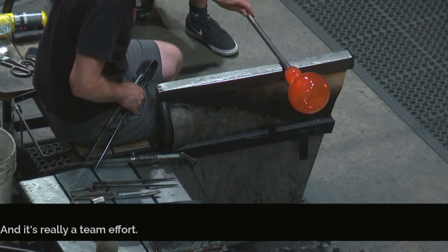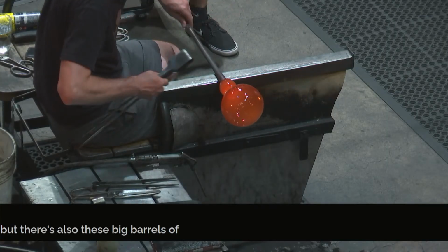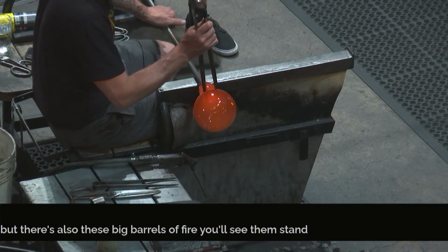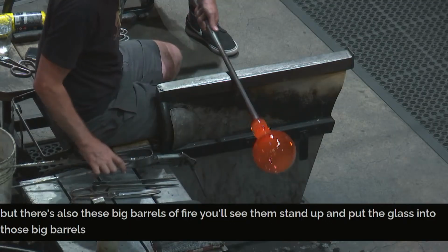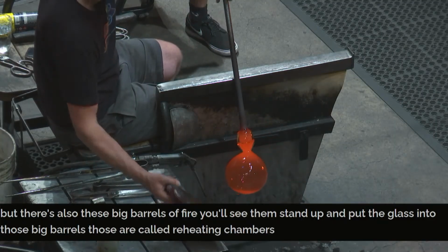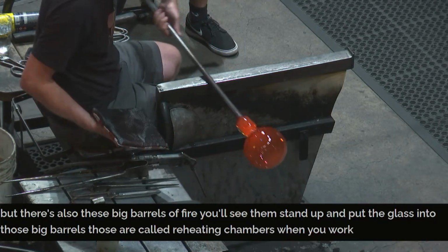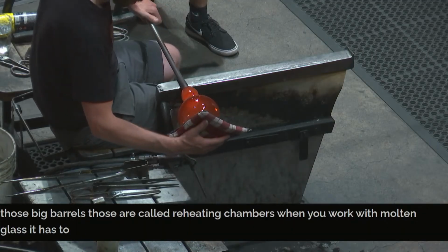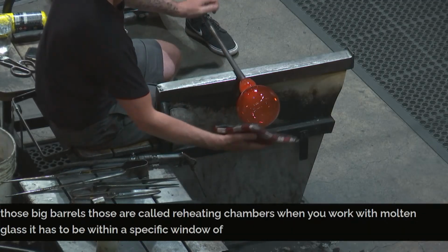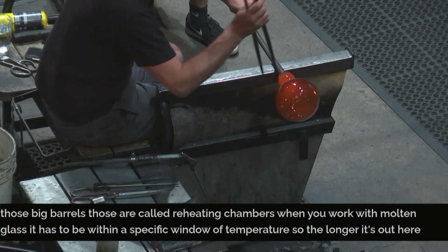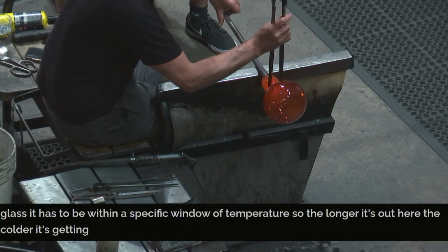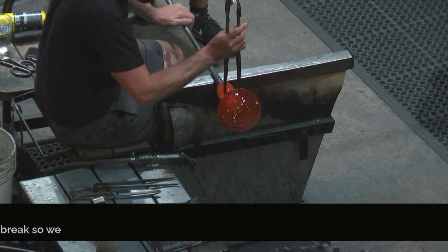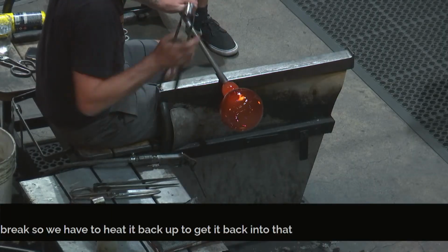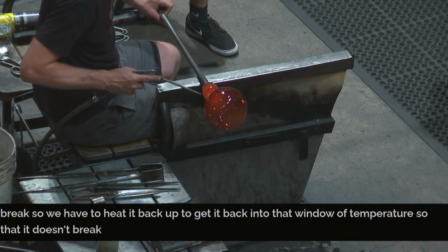But there's also these big barrels of fire. You'll see them stand up and put the glass into those big barrels. Those are called reheating chambers. When you work with molten glass, it has to be within a specific window of temperature. So the longer it's out here, the colder it's getting. If it gets too cold, it will break. So we have to heat it back up to get it back into that window of temperature so that it doesn't break. If it gets too cold, it breaks.